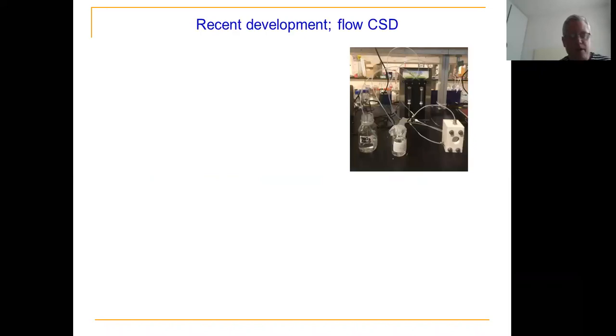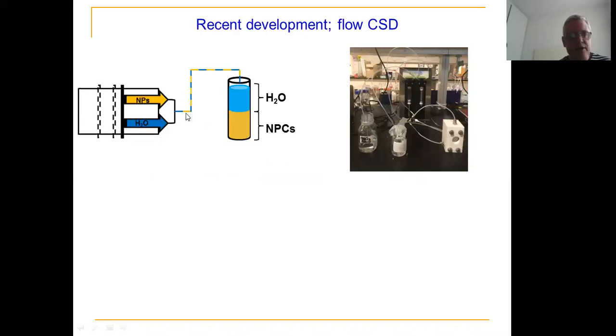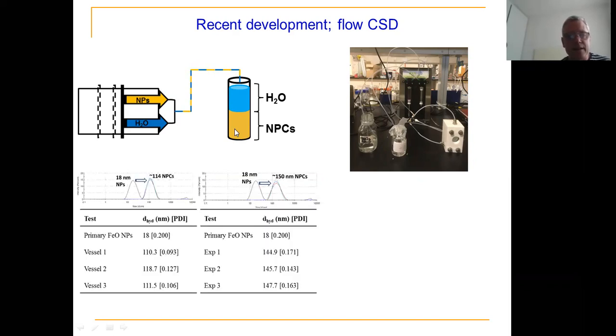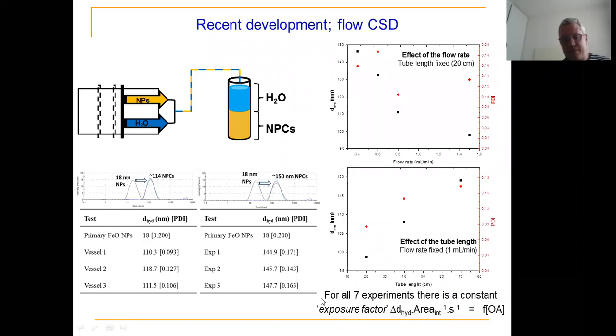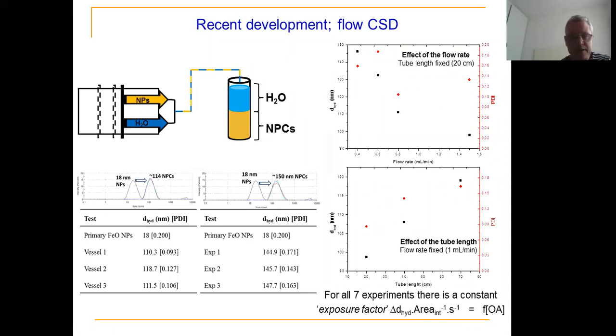More recently, because we have chloroform and water streams, we can perform the reaction in a microfluidic device — pushing chloroform with nanoparticles in one stream and water in the other, forming monodisperse slugs each acting as a small reactor. We can separate the clusters at the end, and find that cluster size is functionally dependent on tube length and flow rates. All experiments collapse onto a single exposure factor relating the surface area and time of exposure, allowing cluster size to be selected simply by choosing tube length.